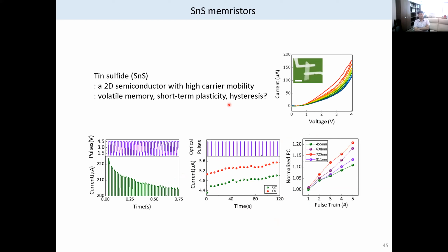I chose tin sulfide. Tin sulfide is quite a popular 2D material these days because it has high mobility. High mobility is always attractive, like black phosphorus and graphene. People already observed this phenomenon: the tin sulfide mobility is quite high, so hundreds of microamperes can flow. But the problem is that reliability is not good. If we sweep this current and then the next sweep, we get different current levels.